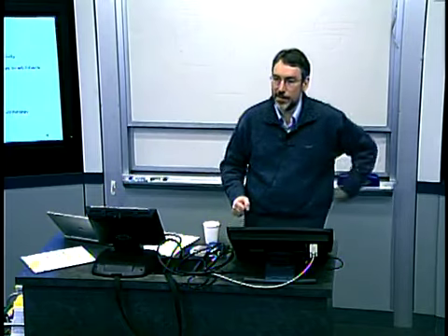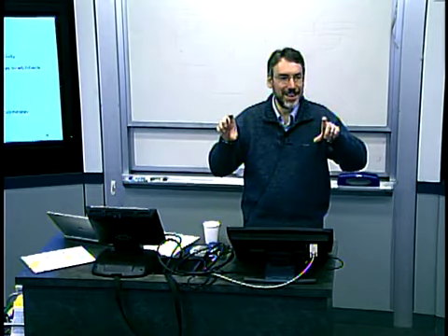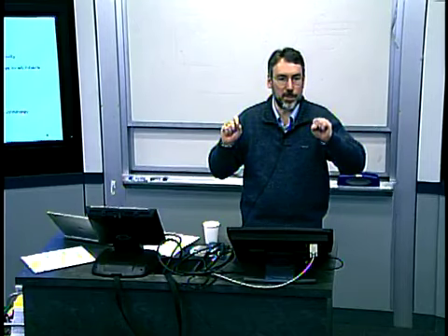Okay, so they are making some measurements of film stress. In fact, the way they make this measurement, I believe, if I remember right, is they measure the wafer bow, and then based on assumed numbers for the modulus, the Young's modulus, and perhaps the thickness, they may measure the thickness separately. They basically calculate or estimate what the film stress is.